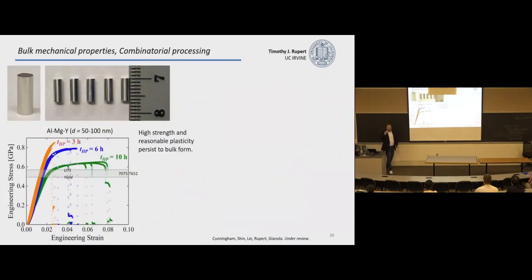Because we can make these things in bulk, we can also do things like bulk compression experiments. These are, again, pieces that you can hold in your hand and see the same thing. So you get high strength and reasonable plasticity from materials in their bulk form. One thing that we're not able to do very well is play with the composition of these materials.